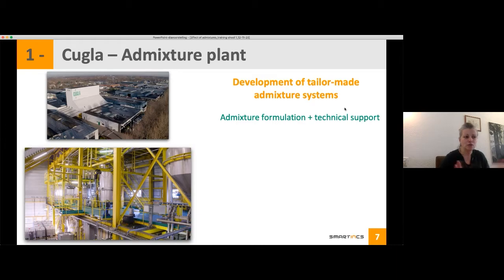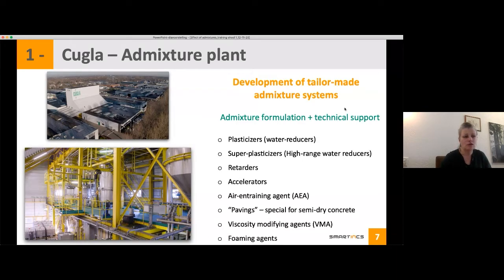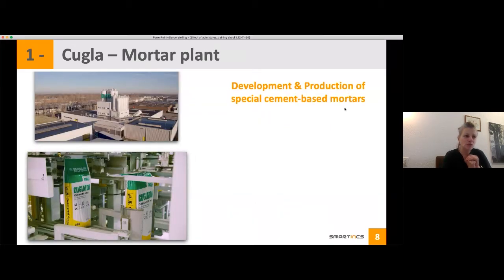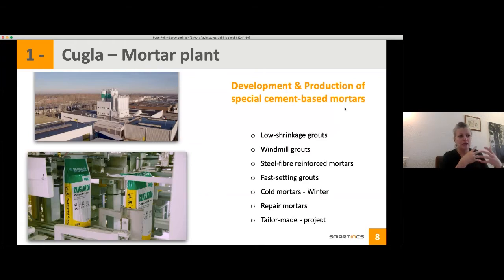About the admixture, we have a wide range of different admixtures we can formulate from. Next to this, we also have mortar plants. So we produce special-based mortar, and there you can think about windmill grouts or fast-setting grouts. Fast-setting grouts are grouts that reach 30 megapascal in 2 hours of cold mortars. And Michael also asked the question how you should do in the winter. If you have special mortar, then it will have the same strength development at low temperatures as at 20 degrees.